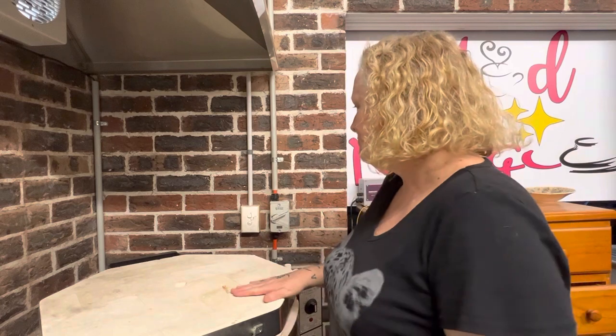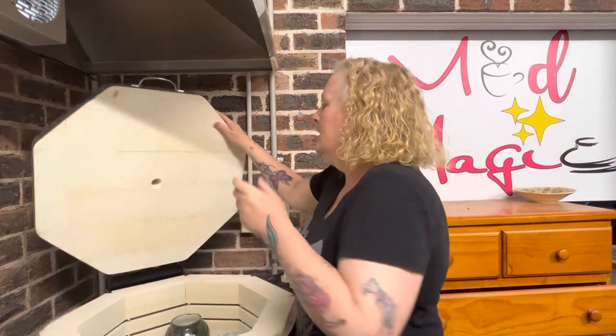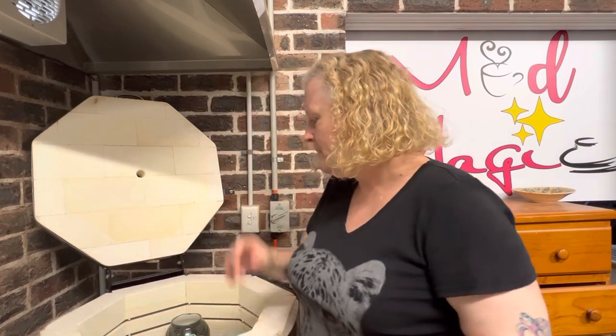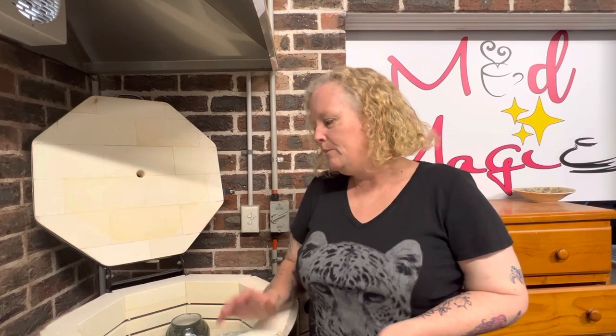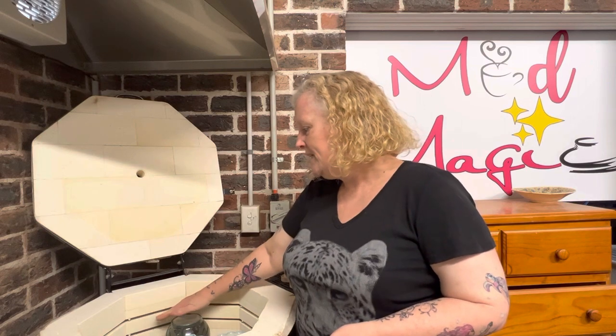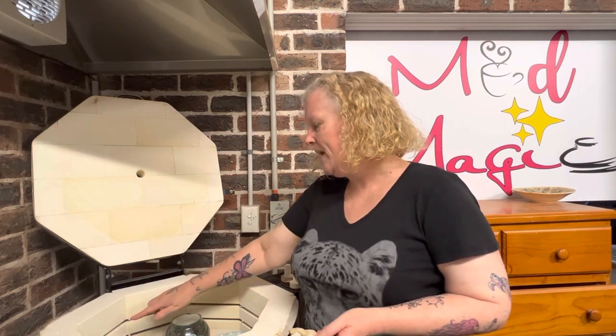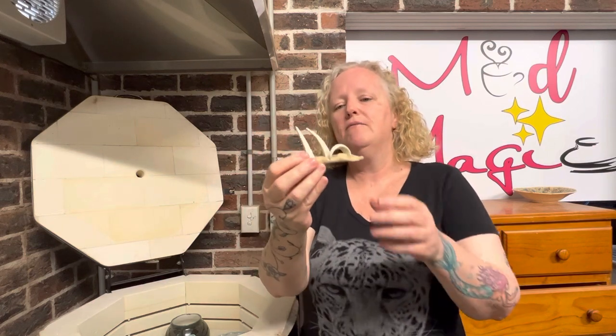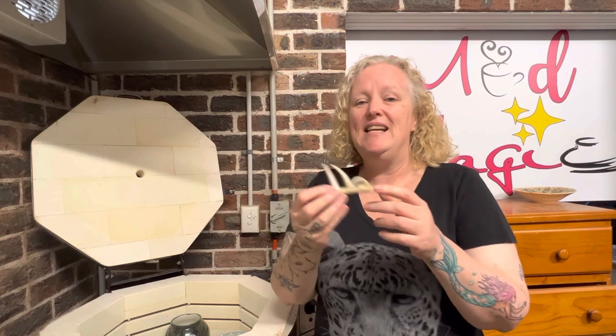Freddie Mercury is very cold — we'll open him up. I've had a look at the top shelf and there's a bit of a mixed bag, but it's pretty good. I've repacked my shelves. Before, I had trouble with the top shelf being really cold — last time it didn't even reach a cone five starting to bend. We got advice that bigger pieces would make it hotter. Looking back at my videos, when only the very top element was showing it was colder. I think if you have at least two elements showing it's better. Today I've got three because I've got bigger pieces, so cone five is definitely gone and six is going — five and a bit. That looks like the answer.